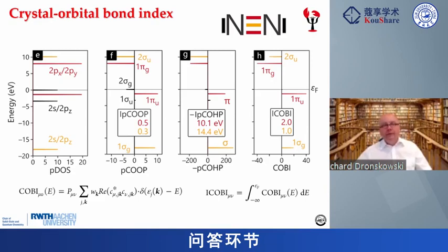So you have a crystal that consists of sodium cations, isolated electrons, which act as anions, and the helium atom is just a spacer. The helium atom prevents the electrons from falling back into the cations. That's it. So you have a salt.